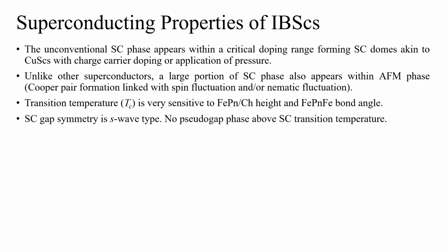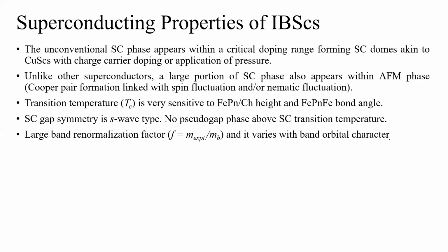Now the gap symmetry in these compounds is S-wave type, very opposite to the copper-based superconductors, which are D-wave type. However, these are not conventional superconductors, so we cannot correlate these S-wave type superconductors with conventional BCS superconductors. We also do not observe in these compounds the pseudo-gap phase, which people usually observe in unconventional copper-based superconductors. The most complex part in these compounds is the large band renormalization factor.